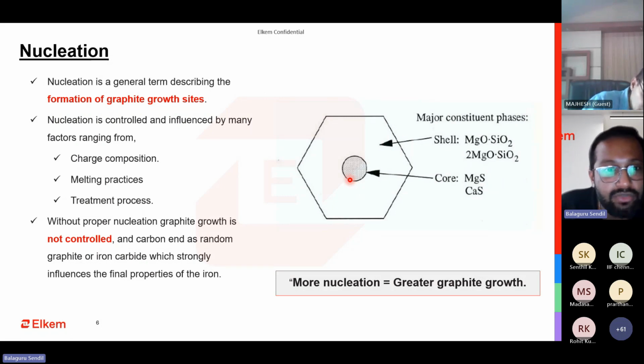This happens when you have a lot of unwanted elements, heavy elements, slag, dross going into it. There is a lot of excess nucleation that happens. So this is very critical. If you look at the core of it, the schematic and the actual image which I showed in the previous slide, the core is always a magnesium sulfide and a calcium sulfide when it comes to ductile iron, and it has a silicate shell. This is what we have seen physically in Elkem using our equipment.